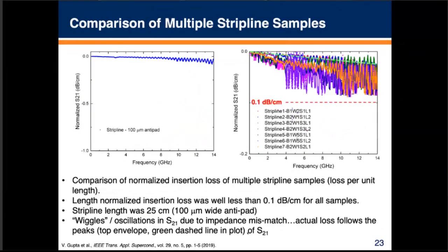In terms of performance, on the left we're showing insertion loss for one superconducting strip line transmission line, and this is in dB per centimeter. This was calibrated onto the cable itself, and you can see this is very, very low loss. So on the right, it's roughly saying we're down below 0.1 dB per centimeter, and that's up to 14 gigahertz. In this case, the strip line was 25 centimeters.